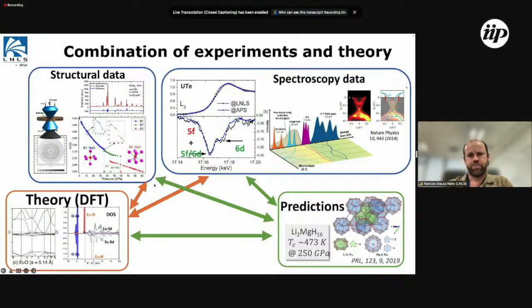But not only that, another possibility is to use this structural information, spectroscopy and DFT, and relate this to the prediction of new phases. For example, this compound was found by ab initio calculations with a genetic algorithm that predicted it would have superconductivity at 473 Kelvin at those pressures. And this is something that we can simulate. We can synthesize those materials that are predicted in theory, or we can have structural information and try to help this prediction to get faster to discover new phase materials.